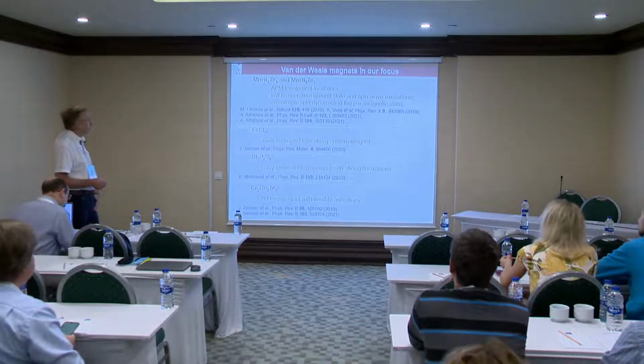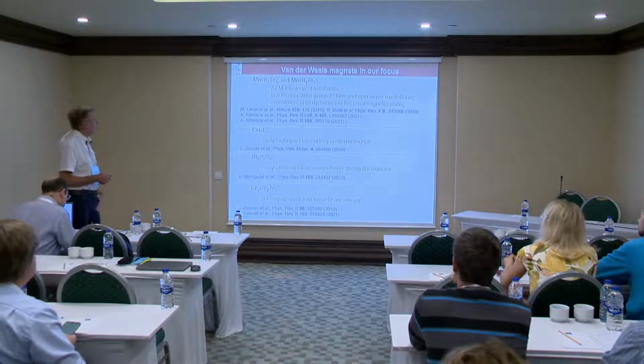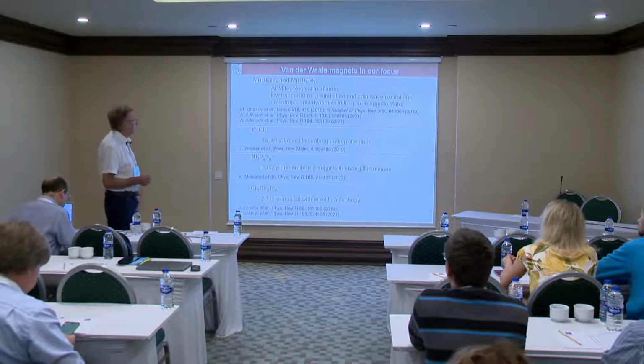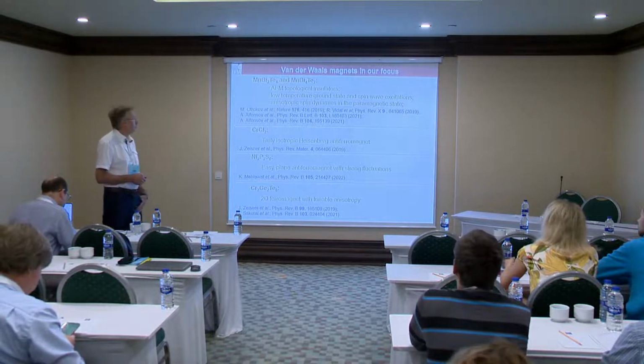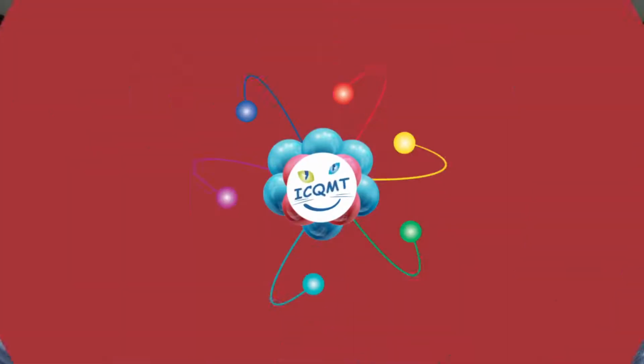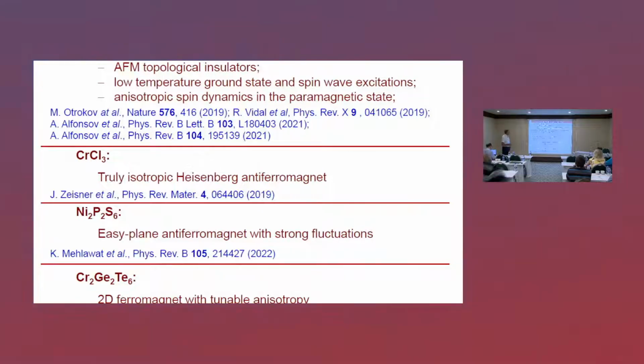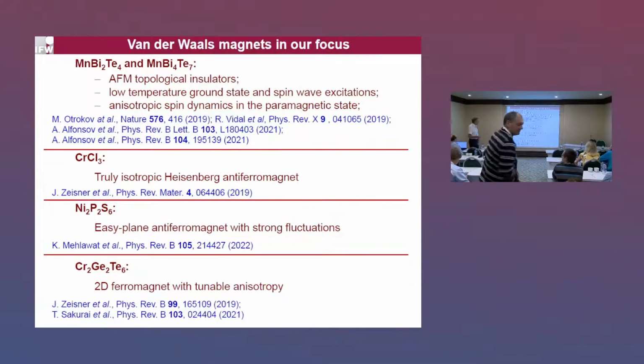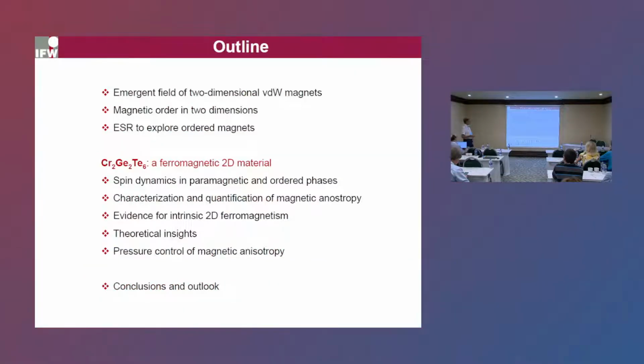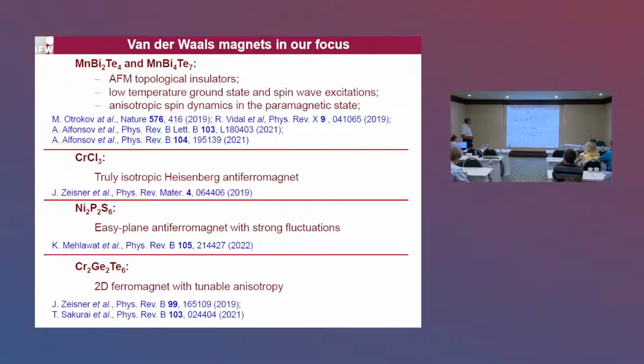quasi-two-dimensional magnets, some of which show very spectacular properties, like, for instance, these manganese bismuth tellurides, which are newly discovered antiferromagnetic topological insulators, where ESR spectroscopy could provide interesting insights on the low temperature ground state and excitations and anisotropic spin dynamics, related to the peculiarities of the non-trivial electronic structure at the surface of these materials. But there are also other compounds which are interesting, which show different kinds of magnetic order.